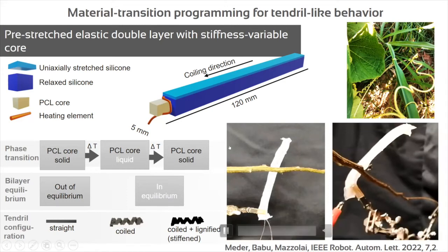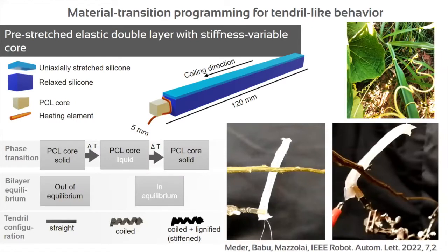What is very interesting is that inside the system there is a PCL core and a heating element. When the PCL is solid, the tendril is in the straight configuration. But when we apply a current to the system, we obtain a melting process. So the PCL becomes liquid, and the pre-stretched silicone layer can release the energy stored. And so what we have is a coiling mechanism.